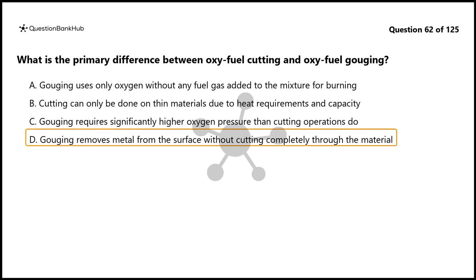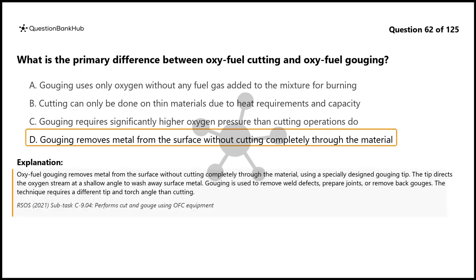The correct answer is D. Gouging removes metal from the surface without cutting completely through the material. Oxy-fuel gouging removes metal from the surface without cutting completely through the material, using a specially designed gouging tip. The tip directs the oxygen stream at a shallow angle to wash away surface metal. Gouging is used to remove weld defects, prepare joints, or remove back gouges. The technique requires a different tip and torch angle than cutting.